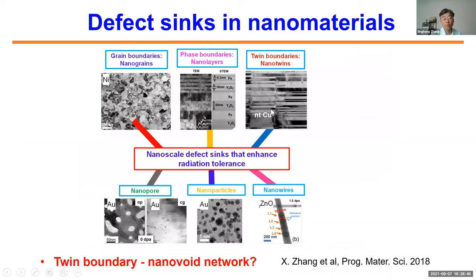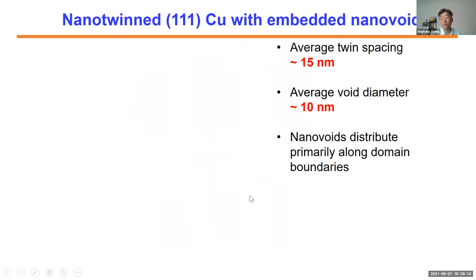And these are a couple of things that have been offered out there in the community by introducing defect sinks. You can introduce grain boundaries, phase boundaries, twin boundaries, nanowires, free surfaces, and all these types of defects can help you to capture or absorb radiation-induced defects. Today I'm going to show some examples of twin boundaries and a little bit of nanovoids, a combination of the two.